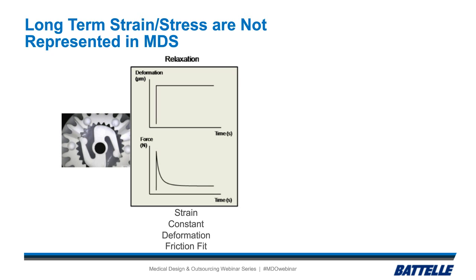So stress relaxation is when you have constant deformation on a part, and if you look at the little picture on the left there of the arms inside the clutch gear, they have constant deformation because that clutch gear is always the same size, and those arms are pressing out against it. But the force is dropping off over time. As that polymer relaxes, it drops off over time. So if you look at that bottom graph, that's what happens over time. So that's stress relaxation. And in this case, if it would drop off far enough, you would lose your clutch and you could get slippage in that little gear.